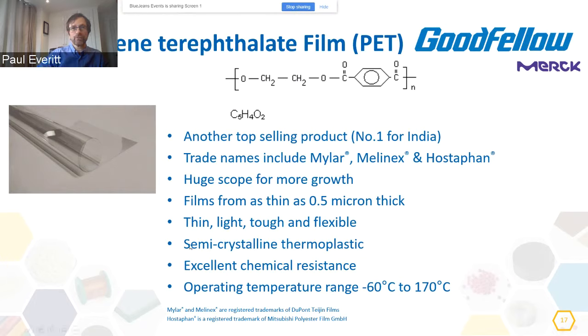And despite people talking about amorphous PET or APET, all commercially available polyester or PET is actually semi-crystalline. Now, that I found personally a bit bizarre, how the industry can call something amorphous when it isn't, but they claim that if it's below 40% crystallinity, they can call it amorphous. Excellent chemical resistance. It's very, very difficult to dissolve, so it's very difficult to characterize for, say, molecular weight, which is why you'll find very few people will publish that information, and generally the best you'll tend to find is intrinsic viscosity.